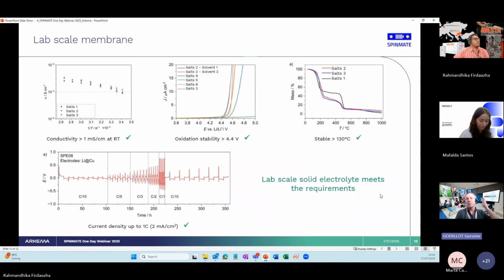So now you can move to the next slide. Thank you. We look at the properties and performances of this film, and they are quite good, as you can see. I will not go into details, but you can see that conductivity at room temperature reaches the target because it is higher than 1 millisiemens per centimeter or very close. The oxidation stability is good. It is higher than 4.4 volt upon the different kinds of formulation we studied. We have some thermal stability as well, up to 130 degrees. And when we did some lithium stripping plating tests, we saw that we can use current density up to 2 milliampere per square centimeter. So roughly, the lab scale solid electrolyte meets the requirements.